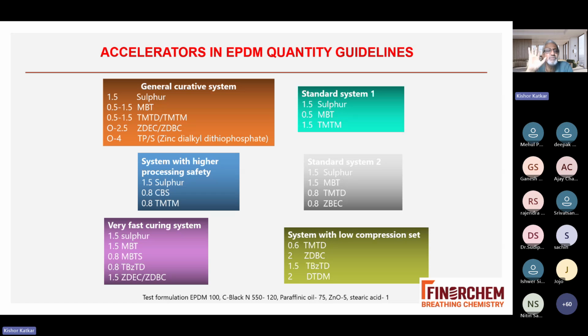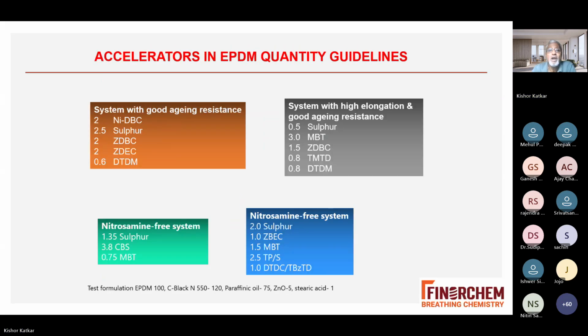These are, I think, general cure systems for EPDM: a standard system with higher processing safety, a fast curing system, and a system with low compression set. Depending upon the EPDM application, you can use these systems with the dosages I recommended, so that you get a good optimum cure and good physical properties without blooming on the surface. Then there are EPDM guidelines: a system with good aging resistance, a system with higher elongation, and nitrosamine-free systems. Here I have mentioned ZBEC and TPS as nitrosamine-free. These are thiophosphates, which have higher solubility in EPDM, do not bloom, and give a very fast cure, so you can use up to 2 to 3 phr in EPDM.